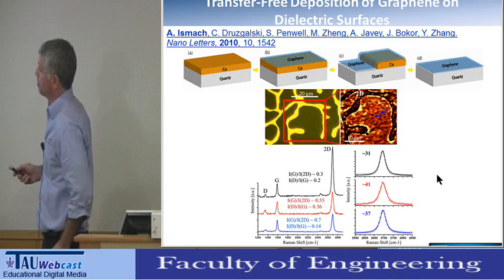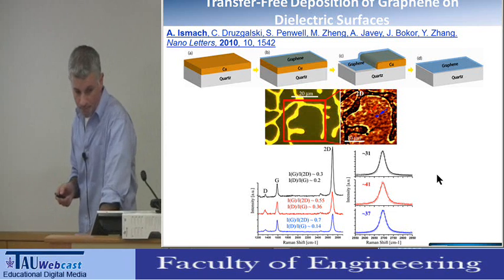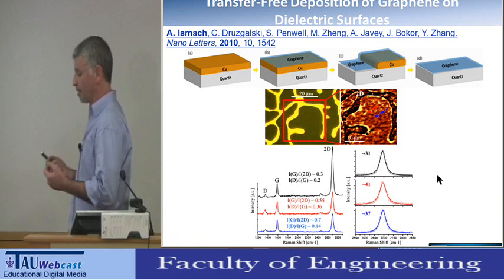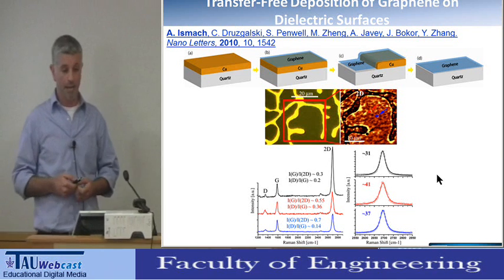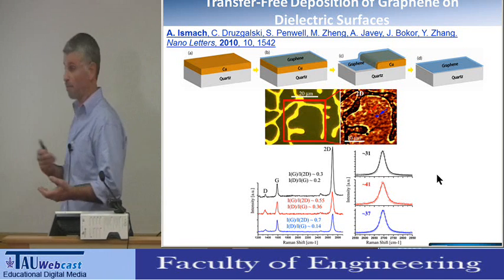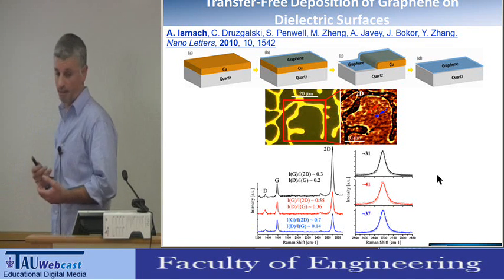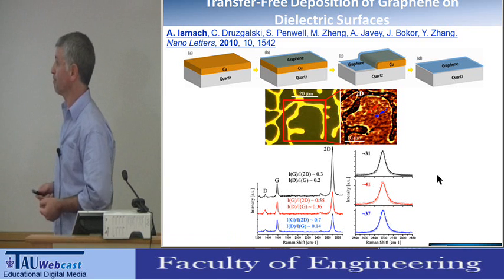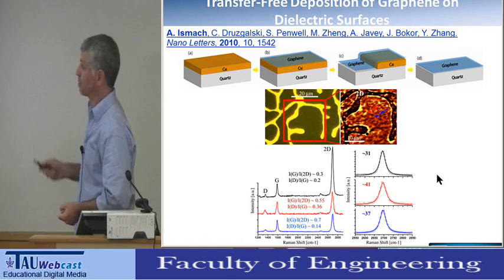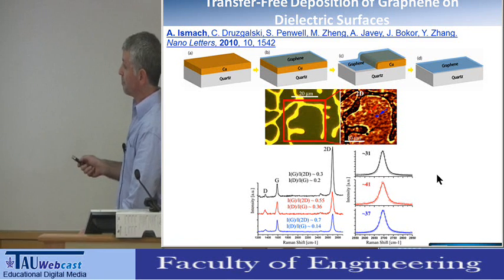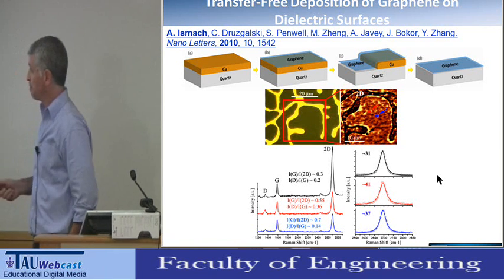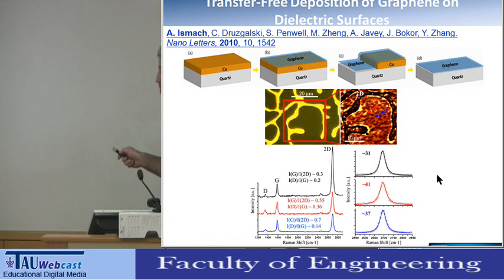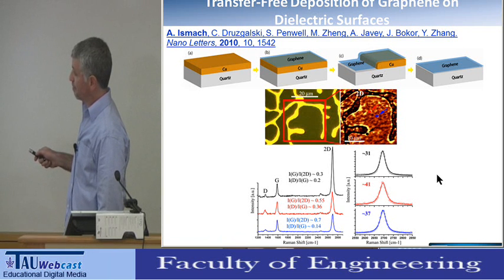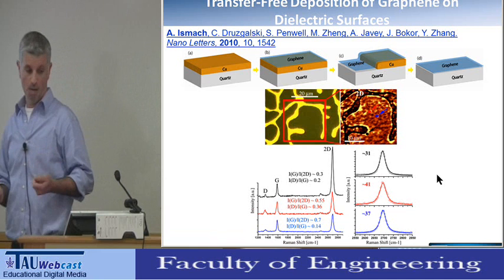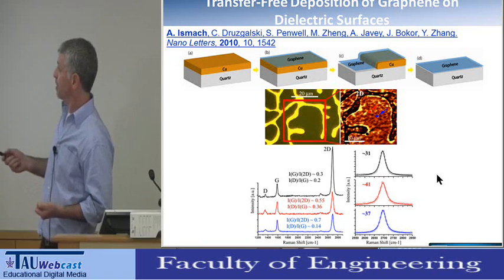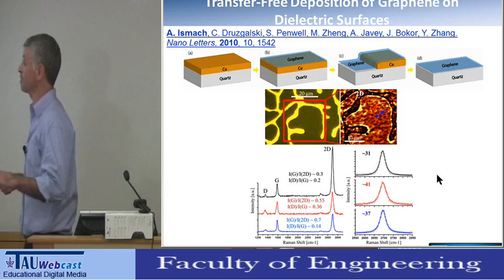Now I would like to talk about some of the work that I did in Berkeley, in which I developed a way for the direct deposition of graphene on dielectric materials, which is a big issue because the transfer process from the metal causes many defects and cracks and deterioration of the intrinsic properties of the graphene. So in this case, I took some dielectric material, quartz, sapphire, or silicon dioxide, and pre-deposited a thin film of copper. Then during the growth and post annealing, by the heating of the copper, we could achieve some control over the wetting and evaporation of the copper, leaving the graphene directly deposited on the surface of the dielectric, as you can see here.